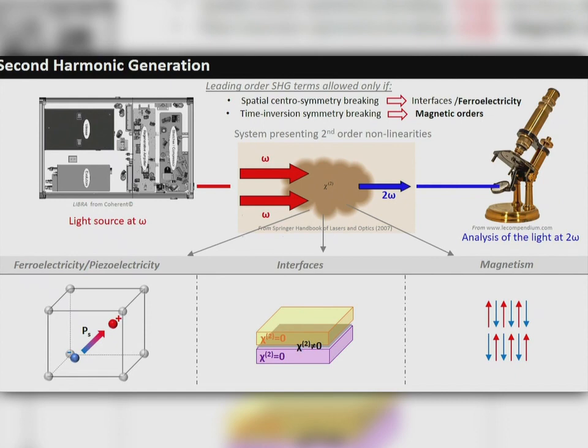And the principle is quite easy. Basically you shine light at omega on the system, and under certain circumstances, it can re-emit light at twice the frequency, second harmonic generation. And I said that at the leading order, this process is only allowed in a system which shows some kind of breaking of inversion symmetry. And speaking of which, it's quite interesting because naturally, ferroelectricity breaks the inversion symmetry. And what you have to know, there is another thing. If you break the time inversion symmetry, then you can have access to some extent to some kind of magnetic order. So that could be a nice tool to investigate it.